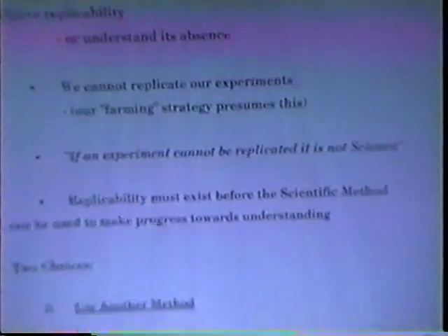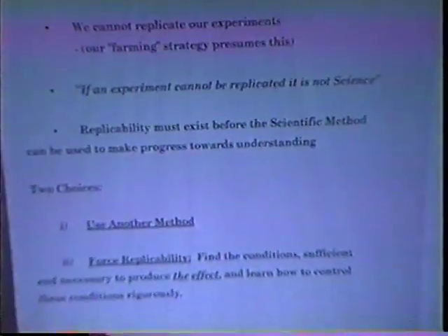And I have here one of the clear imperatives in this field: the need to achieve replicability, or failing that, understand its absence. Why are the experiments not apparently replicable? We simply state we cannot replicate our experiments. We at SRI, at least, cannot replicate our experiments. And our strategy for performing our experiments is based precisely on the fact that we are not able to replicate. We start a farm of electrodes. We start 8 to 12 electrodes in identical calorimetric cells, put them to work in what we call a farm, and we simply select the ones which happen to behave well with respect to loading to put into our calorimeters. We expect not to achieve replicability.